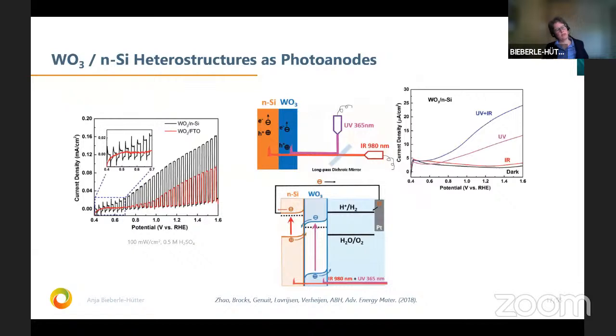Okay, then we said, okay, we are usually depositing on FTO glass samples, but it would be nice to use also silicon samples. And you think also again regarding applications, and also with respect to the effect of getting better performance due to the Z scheme. So we deposited the tungsten oxide on these FTO glass samples and on silicon samples, and received a higher performance on the silicon samples.